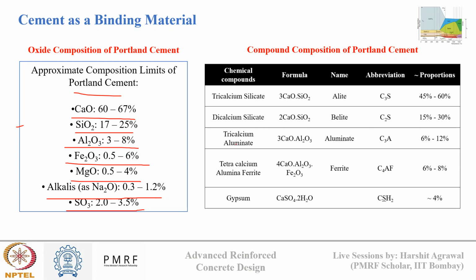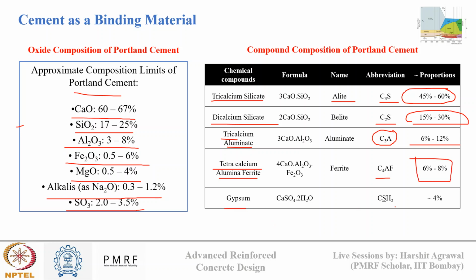Now these formed oxides blend into a solid solution to give different compound compositions that are shown in this table. The first compound is tricalcium silicate, also known as alite and represented by C3S, and it is in the proportion of 45 to 60% in normal ordinary Portland cement. Then we have dicalcium silicate represented by C2S, which is in the range of 15 to 30%. Tricalcium aluminate is represented by C3A, and it is in the range of 6 to 12%. Tetracalcium aluminoferrite is represented by C4AF, and it is in the range of 6 to 8%. And gypsum is present at almost around 4%.